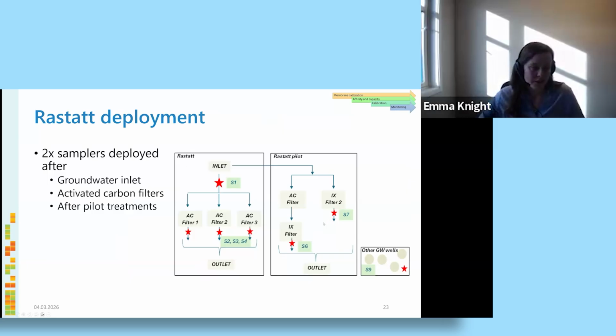And in terms of the Rastatt deployment, we did 2 samplers in each of the red starred locations. So this was after the groundwater inlet, after the activated carbon filters, and then also after the pilot treatment plant, the pilot treatments. In this case, I'd also like to mention that there's 3 activated carbon filters here, but in rotation at the facility, there is 4, with 1 always being out of rotation, and they all have different ages that the activated carbon has been in residence for. And this will be important in a minute.